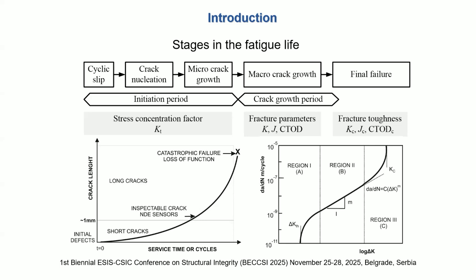So as you know, we can do experiments and obtain the crack length with respect to number of cycles. And then from this we can design the crack growth rate diagram. And from this diagram, we can assess, for example, Paris equation constants or any other power law constants.